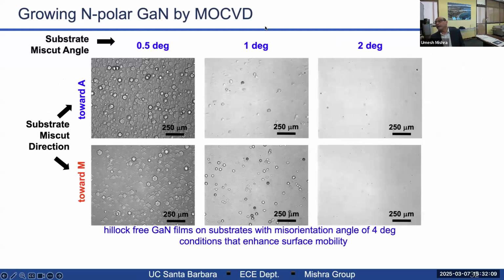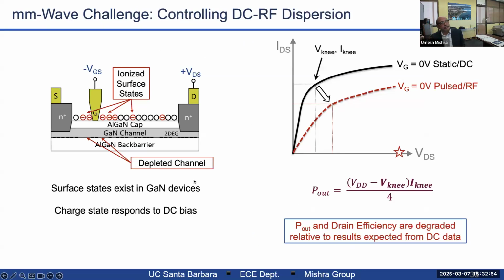So growing nitrogen polar GaN by MOCVD is not easy because the surface mobility of the gallium atoms is low when the surface is nitrogen polar, because the nitrogen atom tends to stick to the gallium and prevent it from finding its natural site, and you get hillocks. Stasia Keller actually ended up doing a seminal study where she looked at growing nitrogen polar on miscut substrates, and we ended up with smooth materials. And now we do 4 degrees miscut to give us process latitude. With that, you end up with a very smooth surface, but you still have these ionized surface states that give you dispersion.